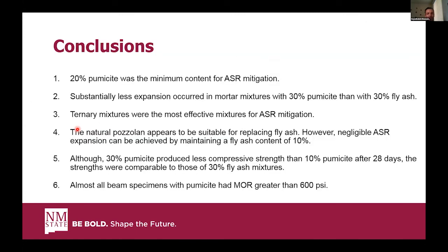Here, I'm going to wrap the results up as a conclusion. First of all, to mitigate ASR, we need at least 20% pumicite, and the expansion of mixtures with 30% pumicite was really less than the mixtures with 30% fly ash. However, ternary mixtures are suggested to be used to mitigate ASR. So at least 10% fly ash is suggested to be added to the concrete alongside the natural pozzolan to have negligible ASR expansion.